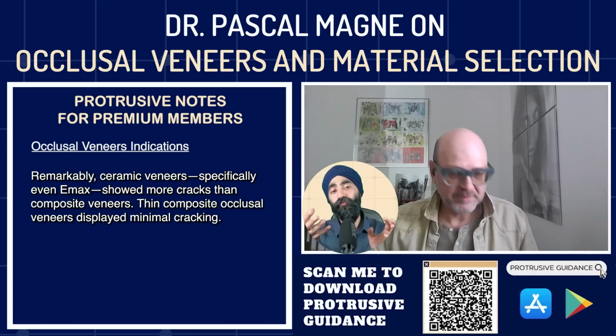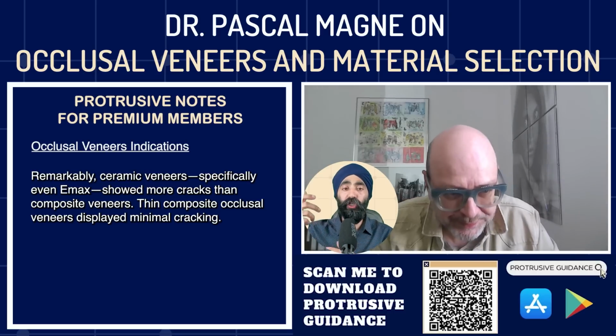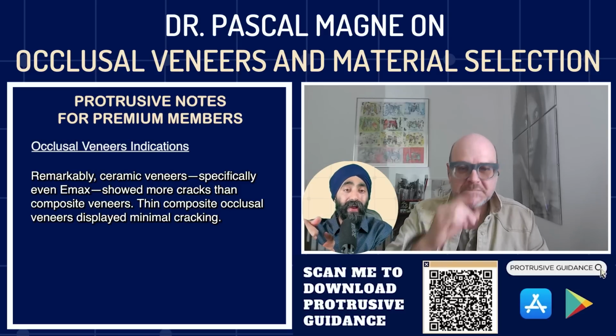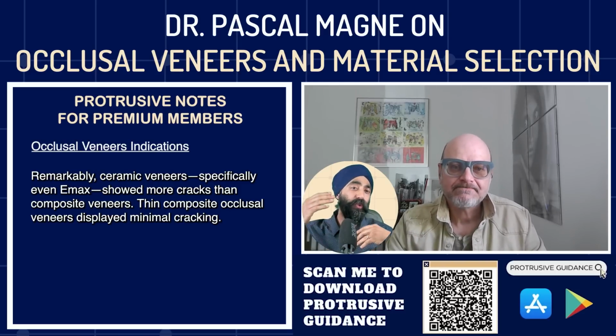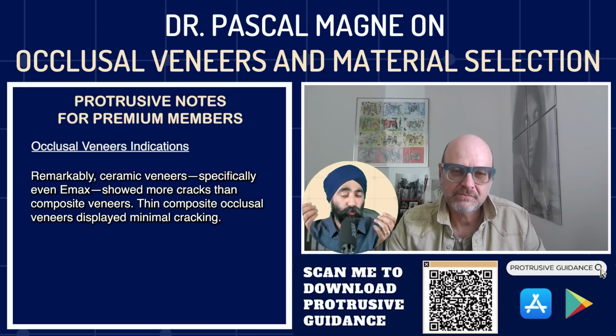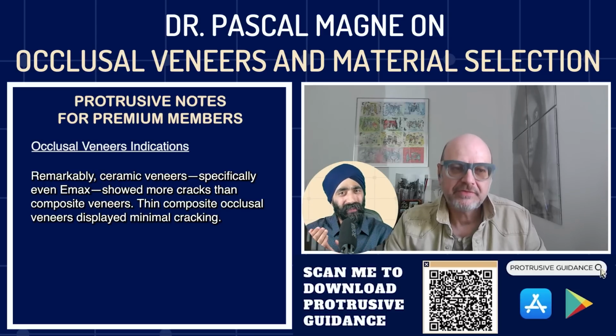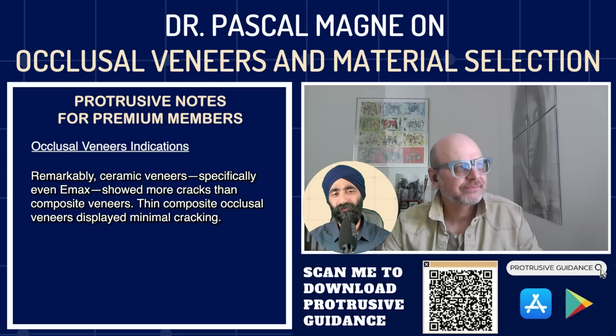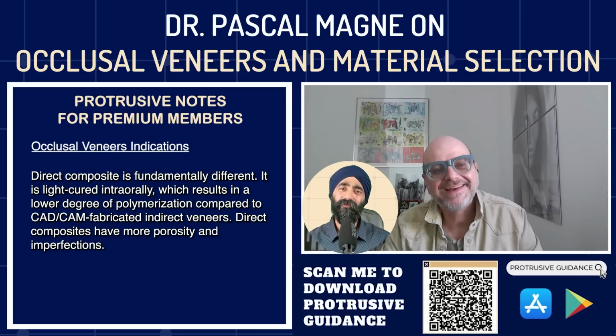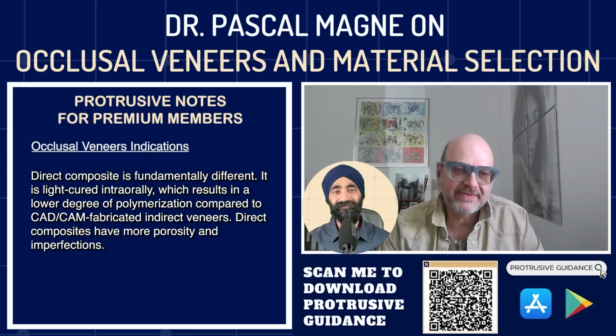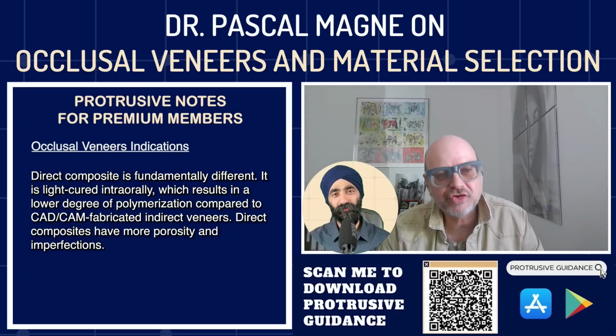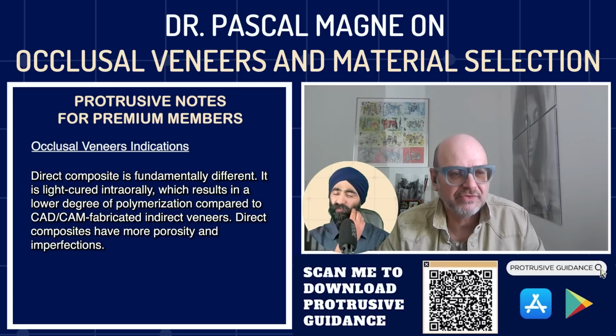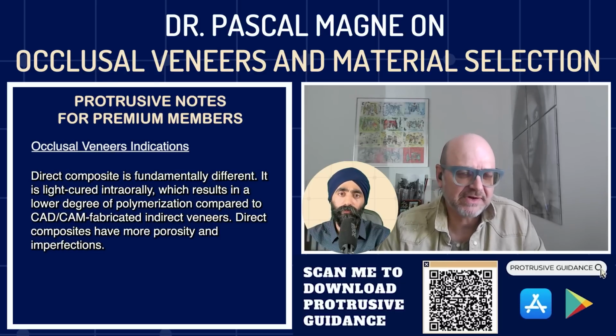Would you have expected the same result if something like Gradia injectable was used in a direct technique and then cured through a stent, but because you were using an indirect composite, that gave it more superior mechanical properties? Would you expect the same result from direct? No. Direct composite is a different animal. Direct composite is light cured in the mouth. The degree of cure is not as good as a CAD/CAM milled occlusal veneer like the ones we did. So the degree of cure is less dense. There are porosities, there are imperfections, right?